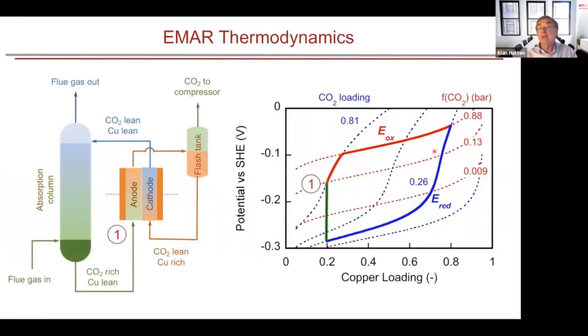At a pressure of about 0.13, a fugacity of 0.13 for the CO2, this is at a constant concentration here. As we start releasing copper into the system, we also begin to start releasing CO2, and we get, at a constant pressure, the CO2 loading going, in this case, from 0.81 to 0.26 in the system.